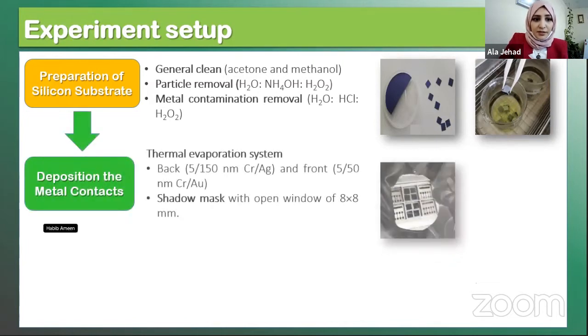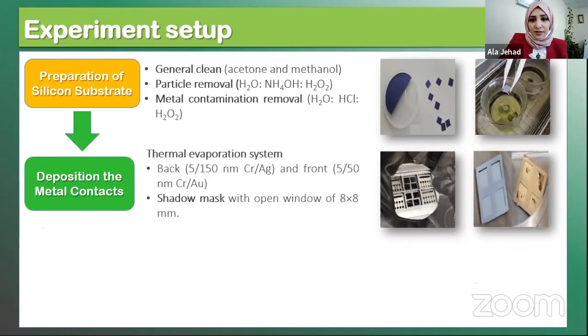Second step was deposition of the metal contact. As you can see in the image, first we design a shadow mask with open area 8 by 8 millimeter. And then we first deposit the back contact, which was chromium with silver, 5 to 150 nanometer. And then we deposit the front contact, chromium and gold.